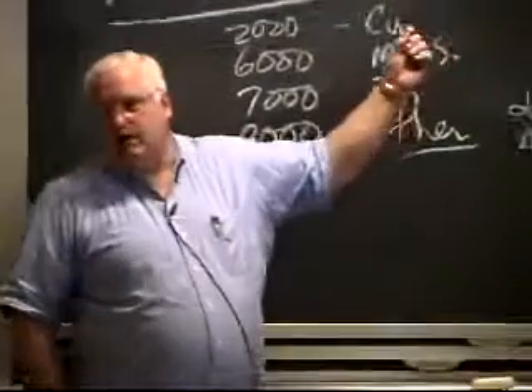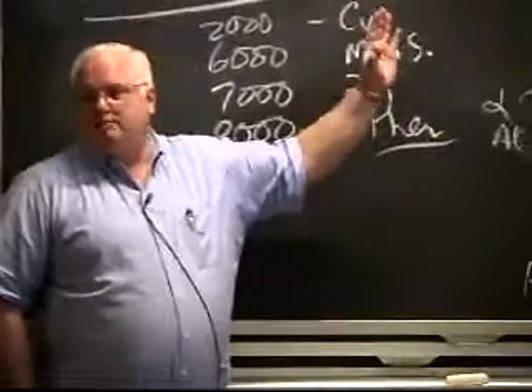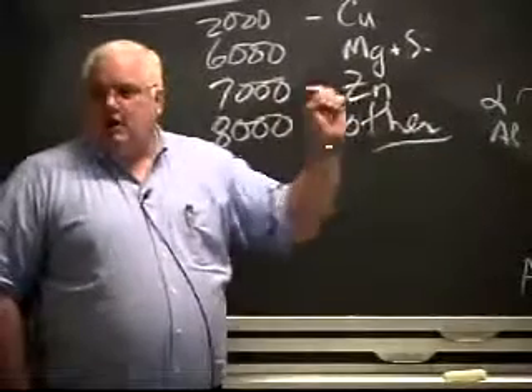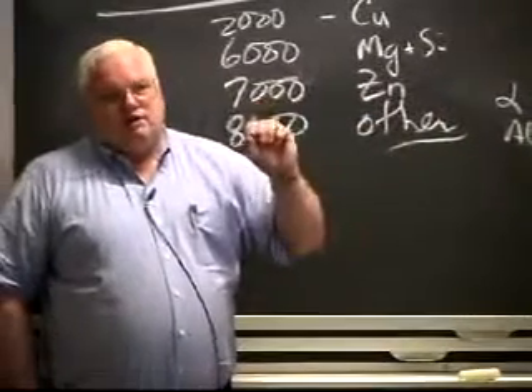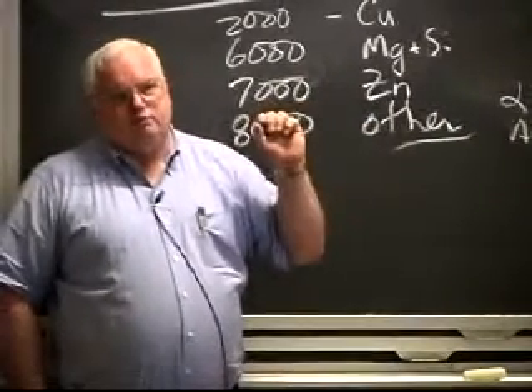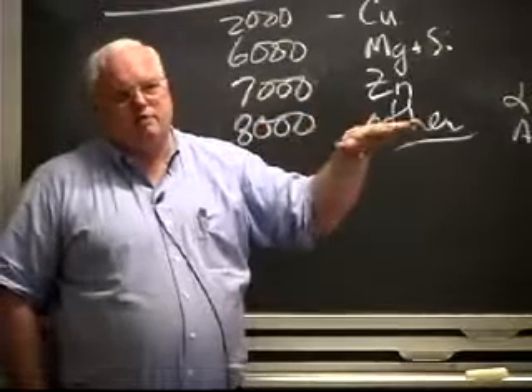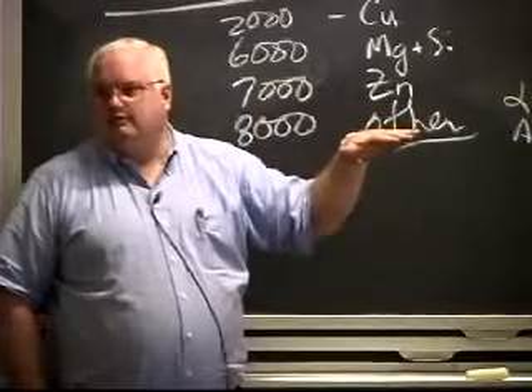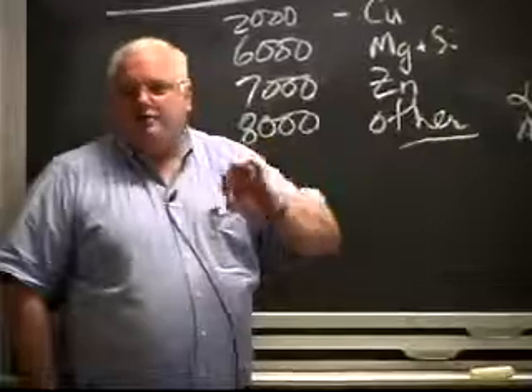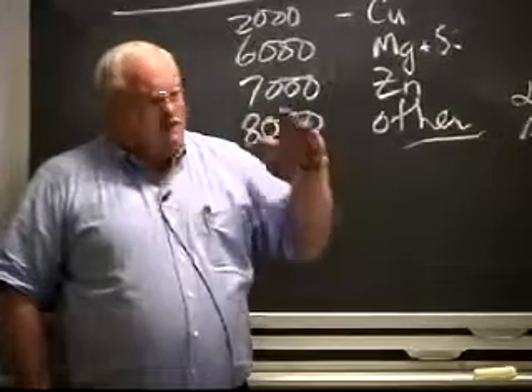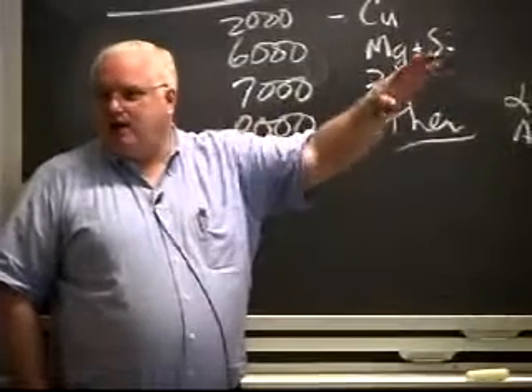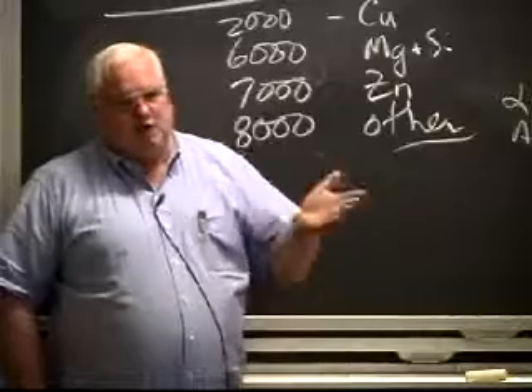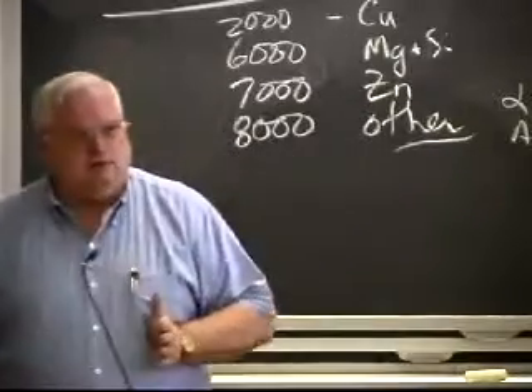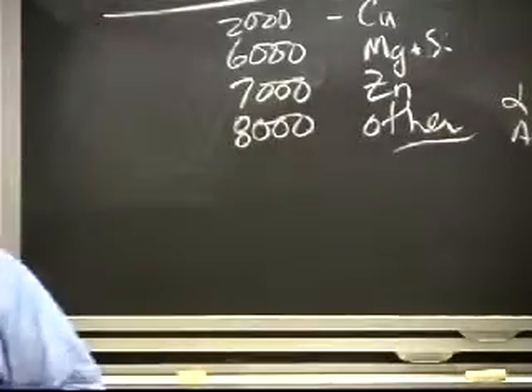Anyway, 10 years ago, the National Institute of Standards and Technology did some scientific studies on the growth of these precipitates in the Wright brothers engine because they had been aging for 100 years at room temperature at the Smithsonian. From that they were able to extrapolate. They had the short-term data, and now they had one data point at 100 years. And it's not often you get a data point at 100 years, on how fast these particles grow.